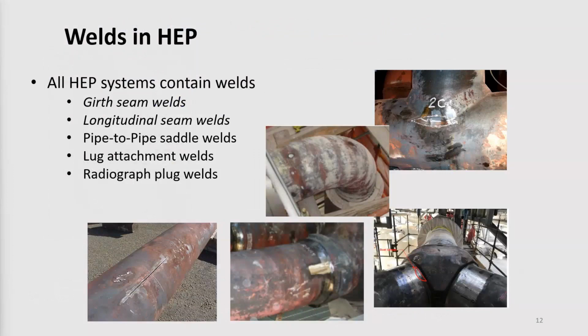Now, as you would expect, there was a lot of work that was done following these failures to try to understand why they did occur, and a lot of the information that came out of that has been critical in defining the inspection programs that are typically applied to these high energy piping systems in order to effectively try to monitor the accumulation of damage over time.